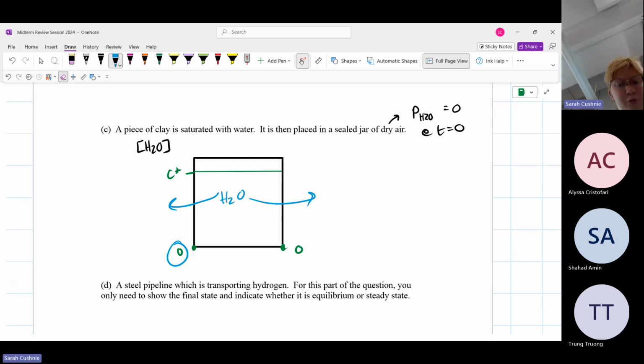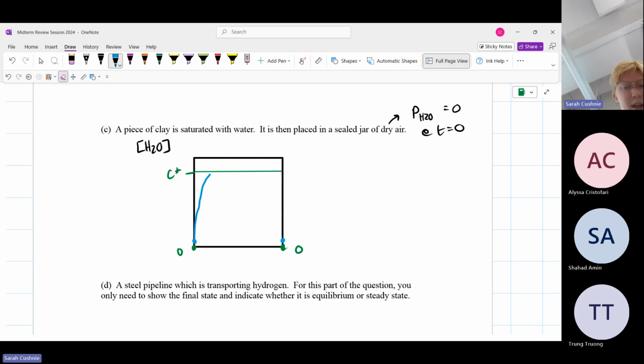So in our short-term solution, it's moved up just a teeny tiny bit, right? Because we still have that initial concentration within the rest of the clay. But over a long time, it's shifted up a little bit more. We no longer have that initial concentration in the clay, and we're going to reach some sort of final homogenized value that again has shifted upwards. This, once again, is an equilibrium.